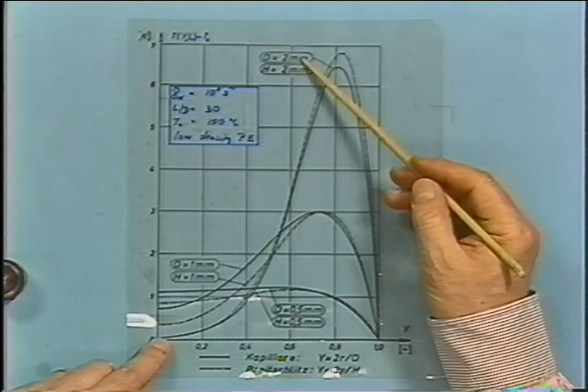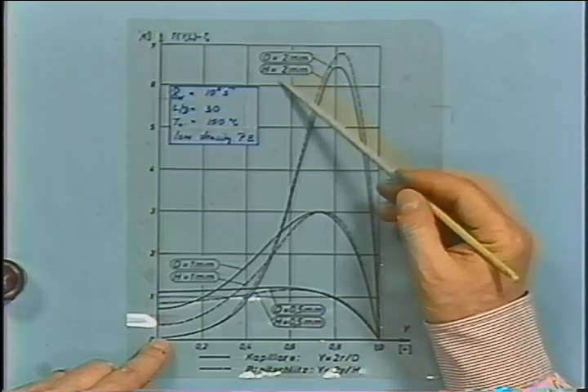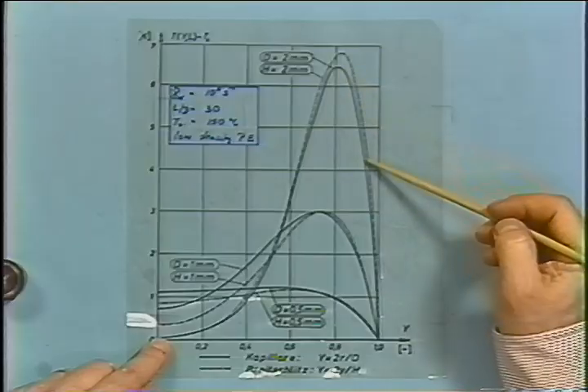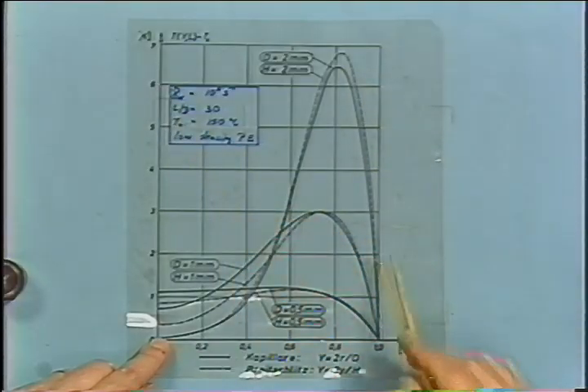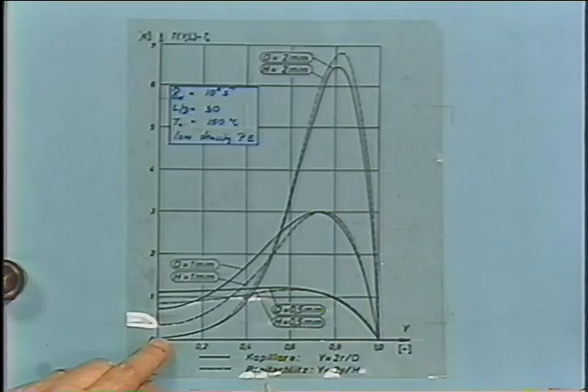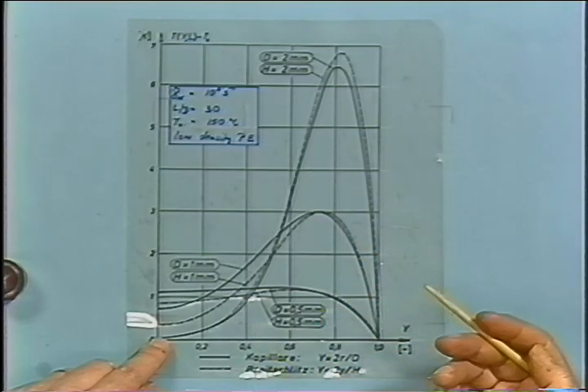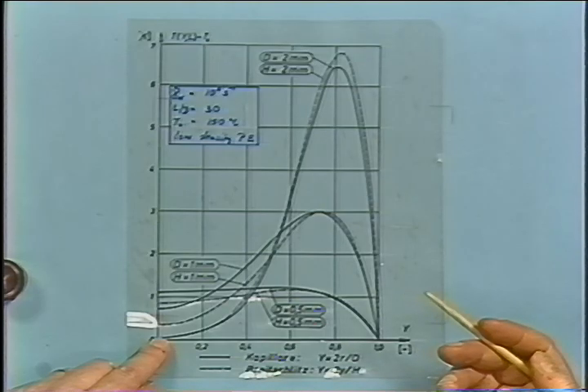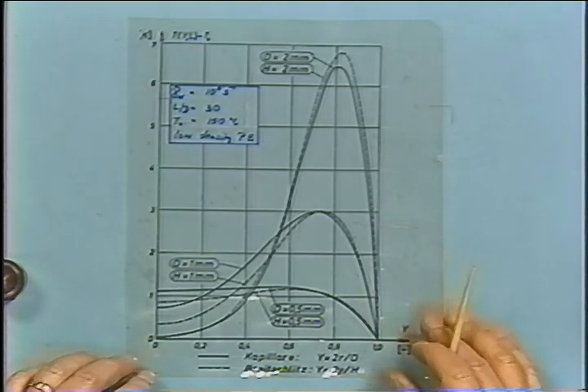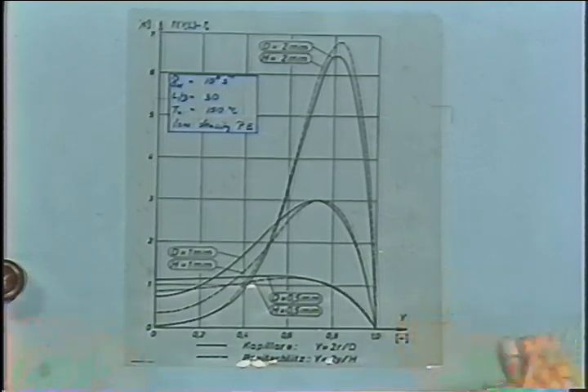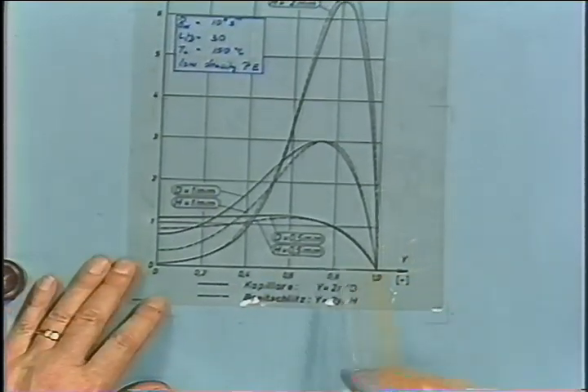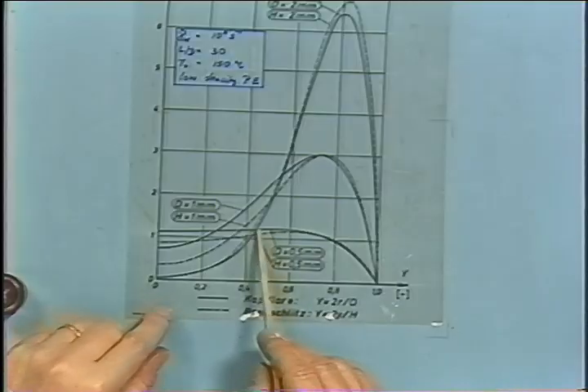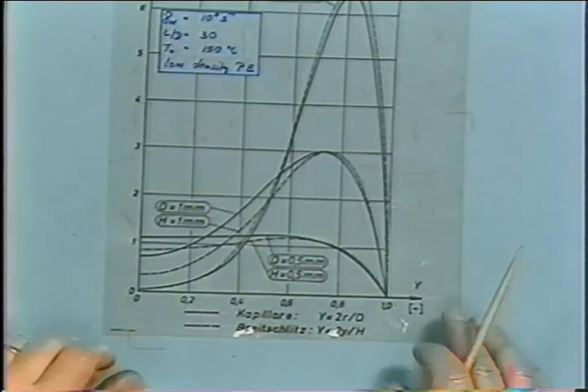Now, for the 2 millimeter capillary or a 2 millimeter slit, I put both of them here, you see tremendous temperature increases. You have 6 degrees, not near the wall, but at some distance. And you can imagine that the viscosity measurement is faulty when doing that, because you have a lubricant layer produced during the experiment, and you measure lower viscosities than you should when you don't analyze the temperature effect. Actually, it's very hard to analyze temperature effects, so we should try to eliminate them. We should try to keep the diameter very small, or the slit very, very thin, and then the temperature effects are very, very small.